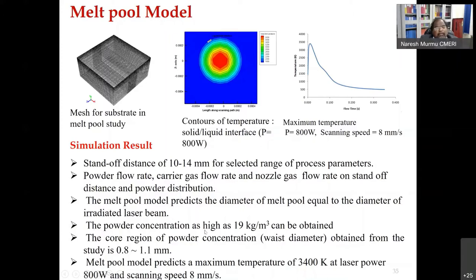Then powder concentration as high as 19 kg per meter cube is possible. Then the region of powder concentration can be obtained in the range of something like 1.1 millimeter. And of course we have found the 800 watt and optimal scanning speed of 8 millimeter per second. So these are some useful findings, design inputs for the system design.